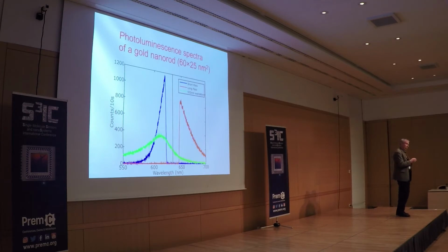If you are able to measure the actual temperature of the heating particles independently from other measurements, you know up to which temperature you can go to kill the cancer cells and not damage the healthy cells. Of course, this is not a demonstration, just a proof of concept of this idea, but this is a way you can easily, without two different sensors, with the same particles, heat and at the same time measure temperature and know that you are not heating too hard.